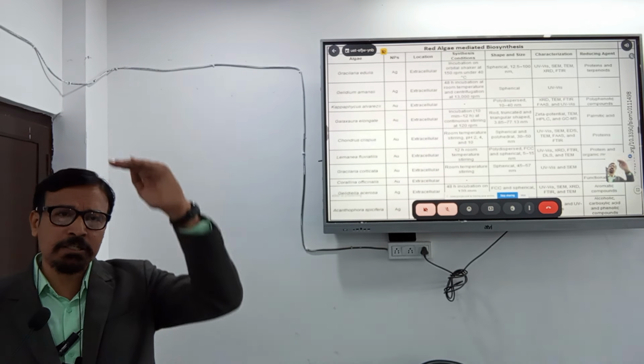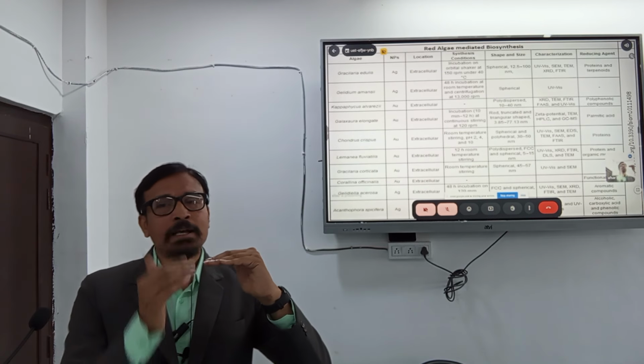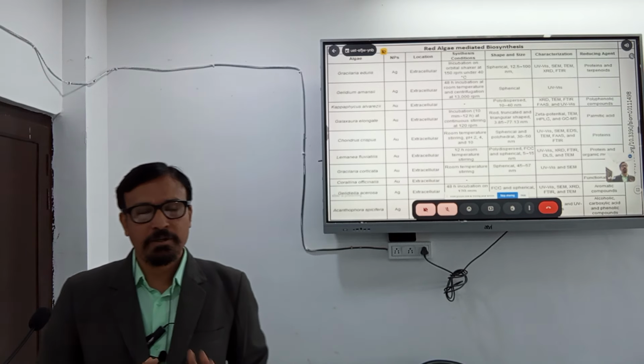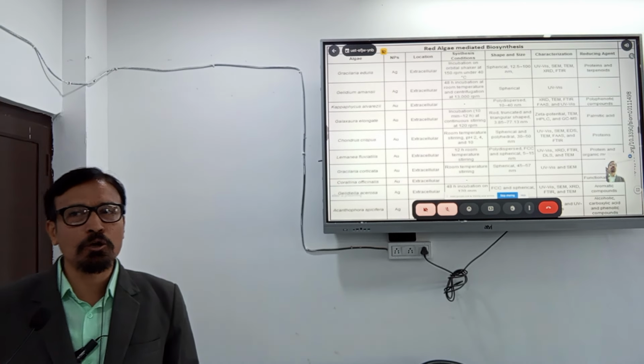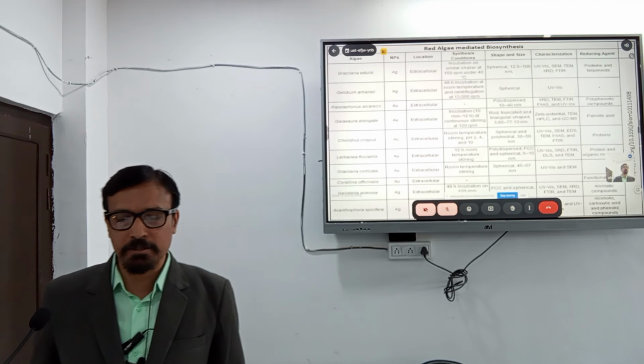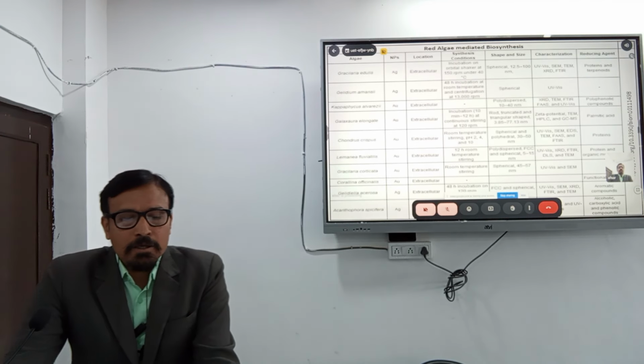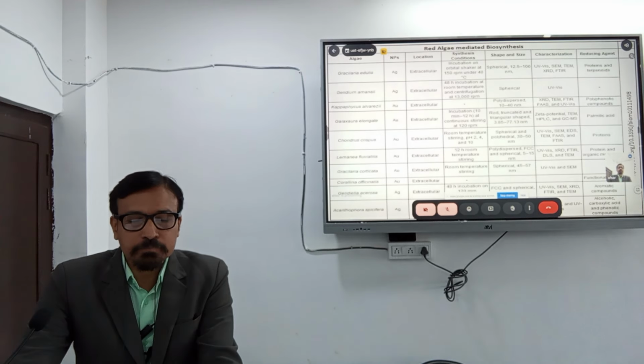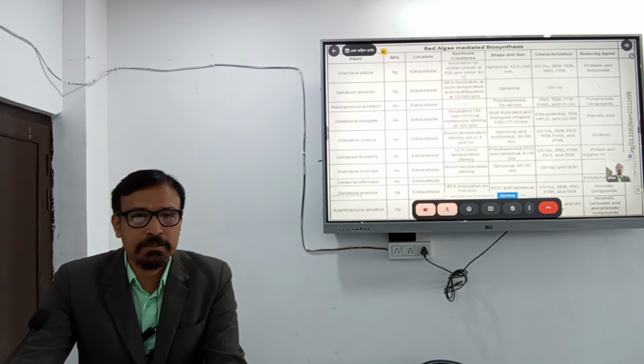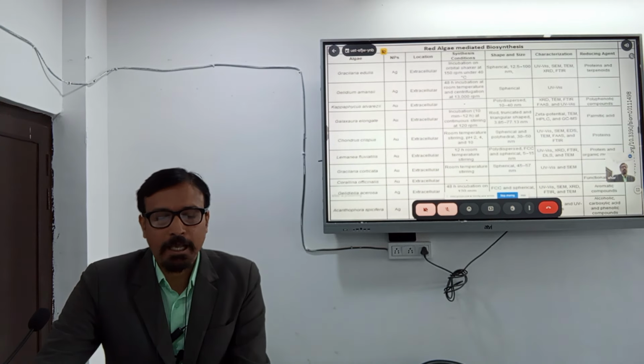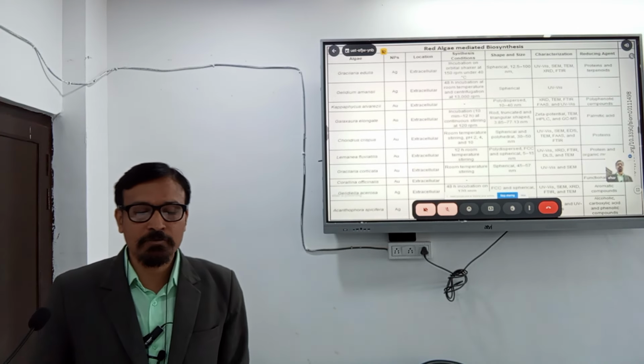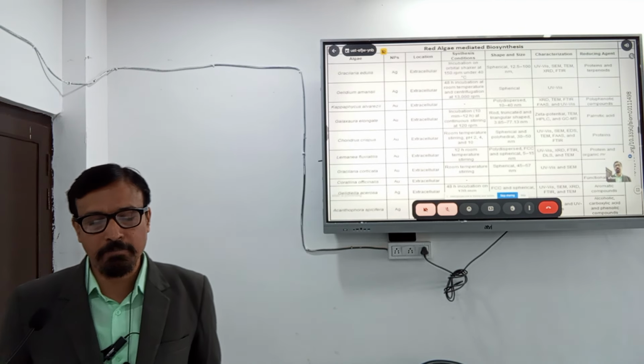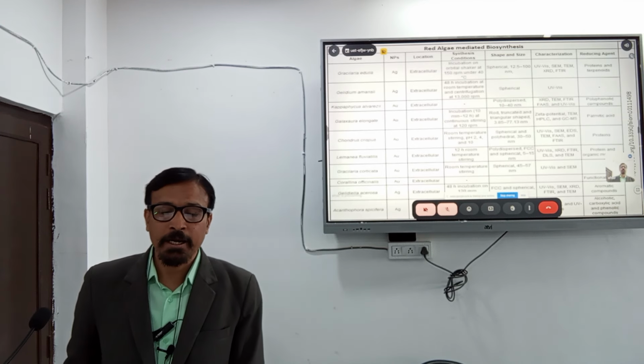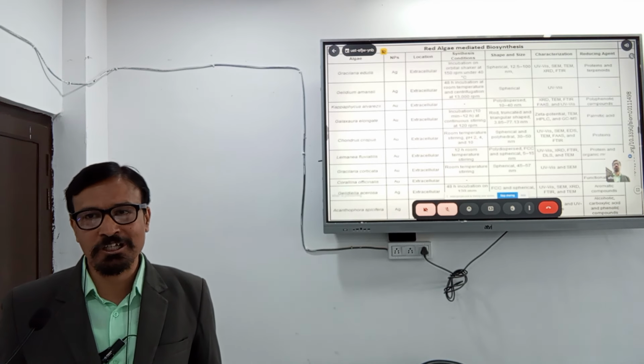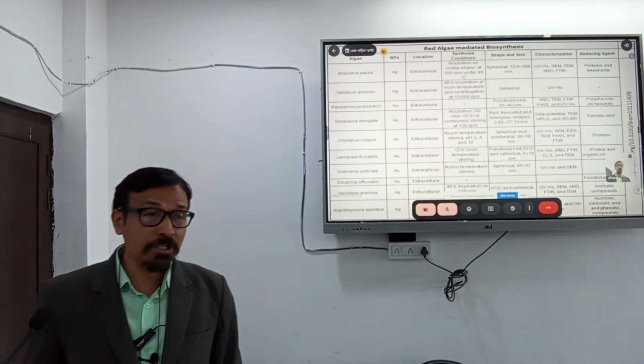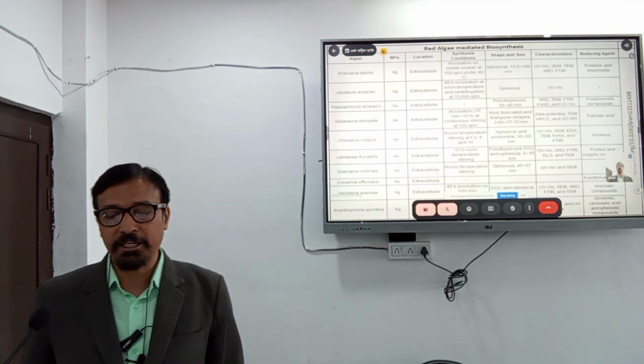So in most cases, the size of the nanoparticles should be less than 100 nanometers. If it is greater than 100 nanometers, then it is no more nanoparticles. Okay. So next is the Lemanea fluviatilis. That is a very difficult to pronounce algae, and the synthesis of these gold nanoparticles can be done with this algae. The location is extracellular, and room temperature and stirring is sufficient for the synthesis of these gold nanoparticles with this Lemanea.